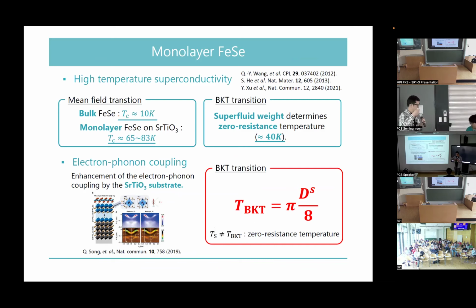This compound was intensively studied because it shows high temperature superconductivity. Although the transition temperature of bulk iron selenide is less than 10 Kelvin, the transition temperature of monolayer iron selenide was reported to be around 60 Kelvin or 80 Kelvin. So this is a high temperature superconductor. But probably these temperatures are not the real transition temperature, because zero electric resistance was observed at a much lower temperature, around 40 Kelvin. So this means that the superconducting transition is determined by the BKT transition characteristic of two-dimensional superconductors. So actually, this is a purely two-dimensional superconductor.